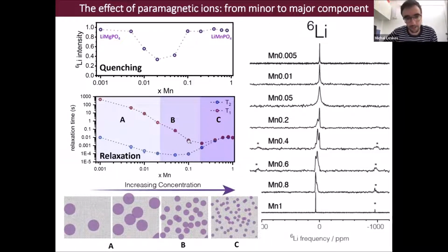But how does this affect the quenching? Of course, if T2 decreases, this basically means that the radius of the quenching sphere is decreasing. And we try to show this here graphically. So with increasing concentration, at some point, the faster electron relaxation time shrinks the quenching sphere until it is so small that we are able to detect lithium sitting next to a paramagnetic center.